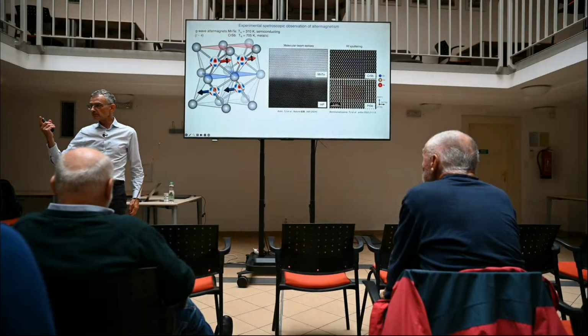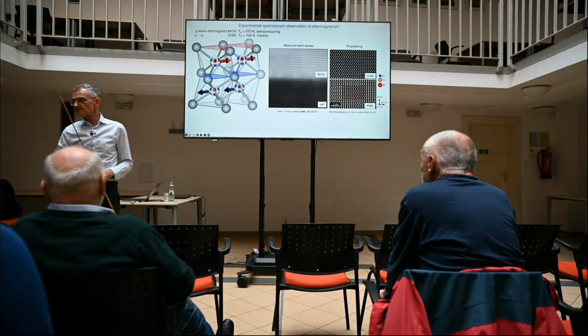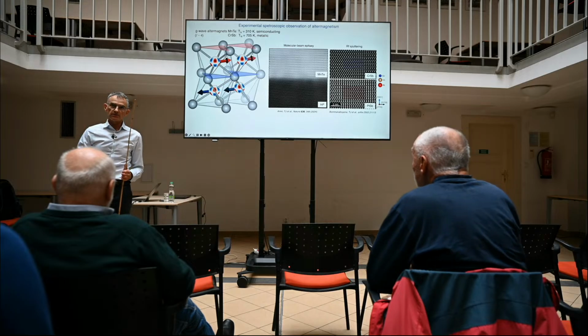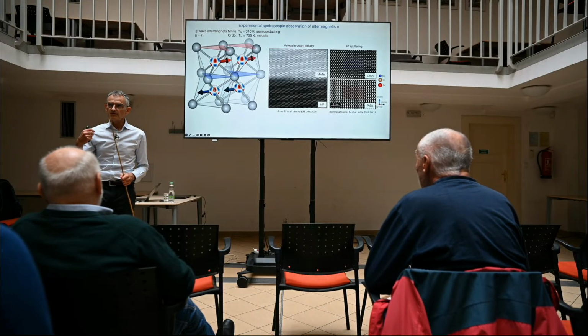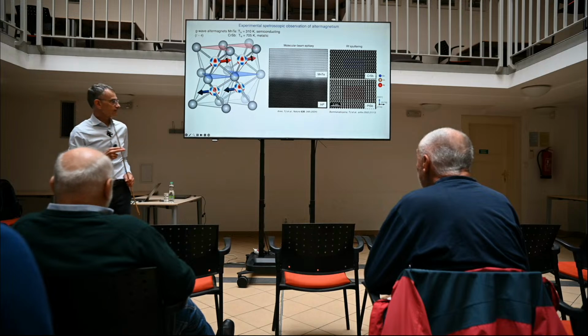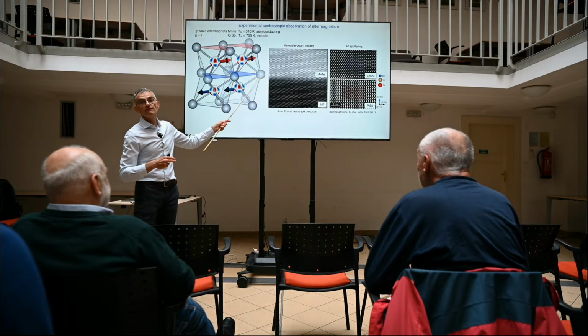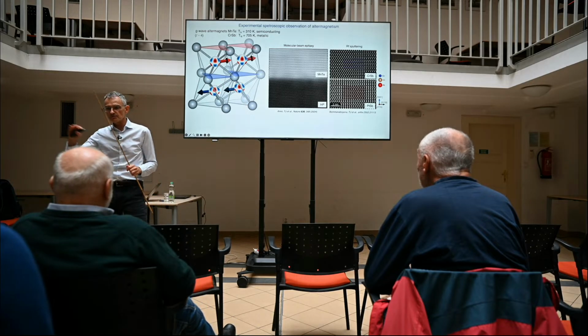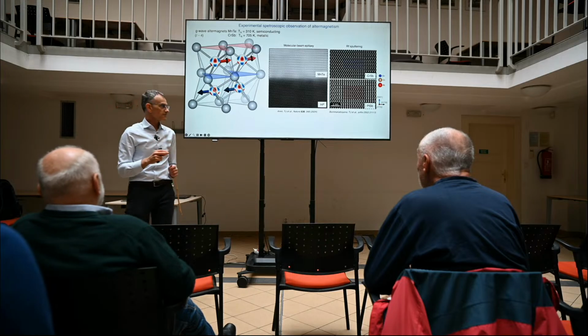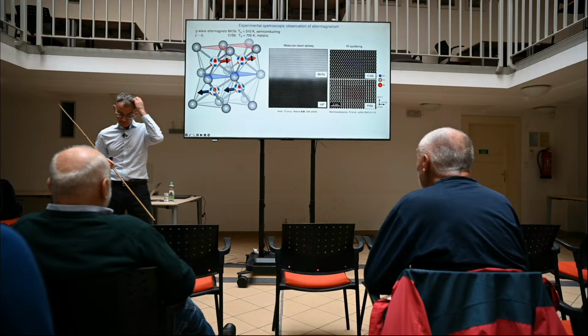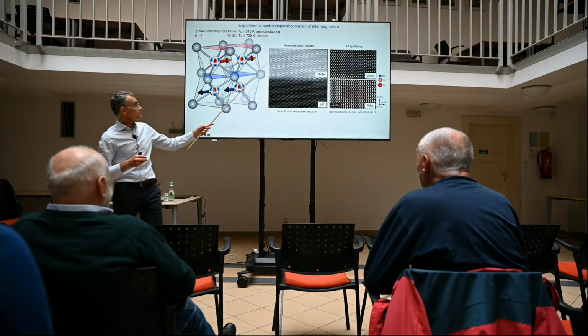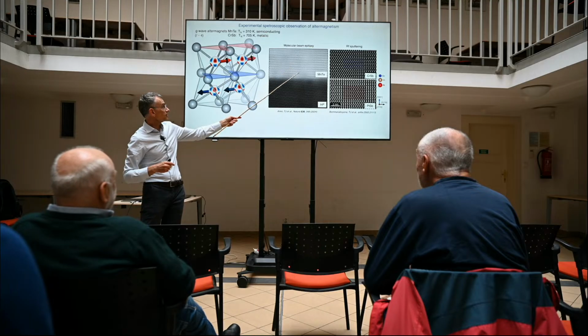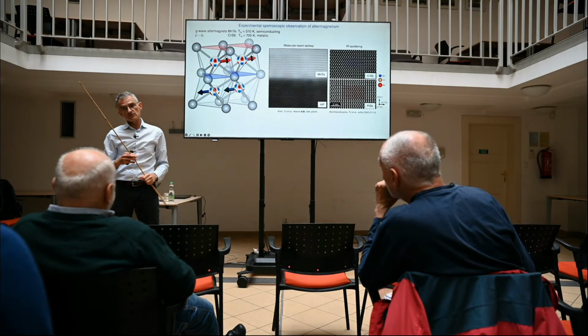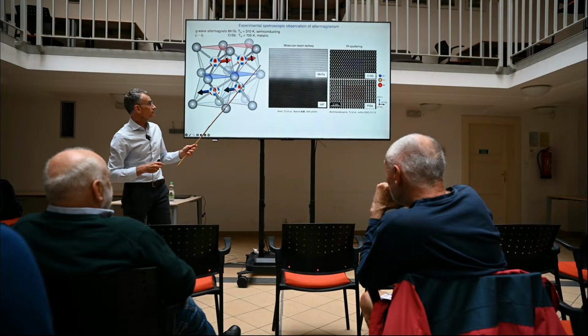Incidentally, on this slide, you can prepare them in bulk by all possible bulk synthesis techniques of materials. The bulk materials tend to be the best quality, but not the most useful for making devices. Therefore, people also like to prepare thin film versions of these materials. All spintronic devices are based on thin film ferromagnets, so you need to be able to develop high quality thin film synthesis of these materials. This is manganese telluride grown by our colleagues in Nottingham by molecular beam epitaxy, which is arguably the most sophisticated method for growing thin films.